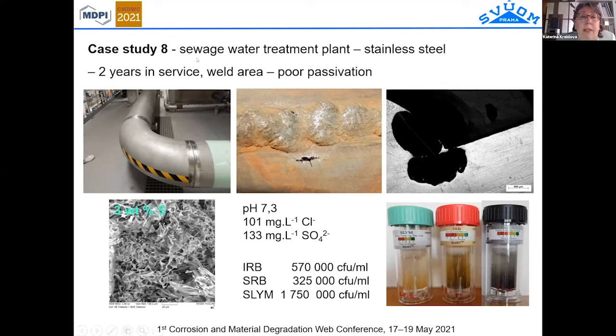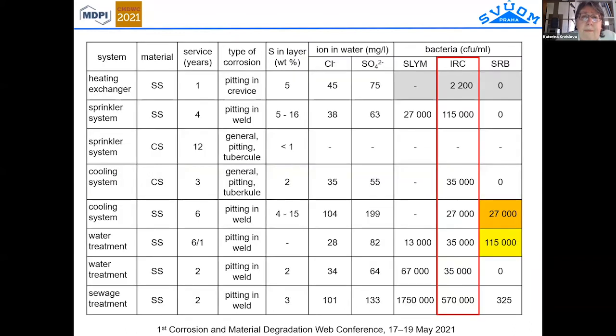It was a pipeline in a sewage water treatment plant, stainless steel, 2 years in service, in a weld area where the inside surface has very poor passivation. Such pitting corrosion occurs, and again we identify a lot of sulfur in this characteristic morphology of the surface. A high content of sulfate was identified in the water, and a very, very high content of bacteria was identified in the water. It is not surprising because it is waste water.